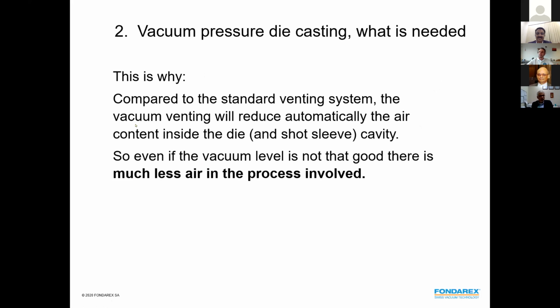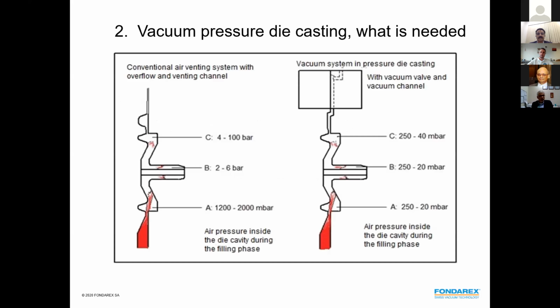So now this is why, compared to standard venting, vacuum venting will automatically reduce the air content inside the die and in the shot sleeve as well. So even if the vacuum level is not as good, we already have less air. If we look at the practice, this is how it looks. Standard venting, which is probably 85% of all pressure die castings made in the whole world, uses overflows and some vents. For many parts, this is fine because the quality requirements are not that high. What happens in such an application?